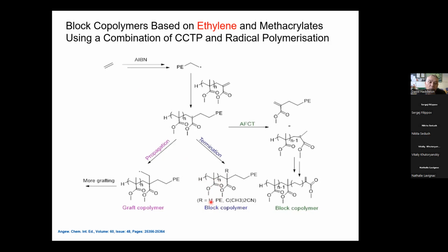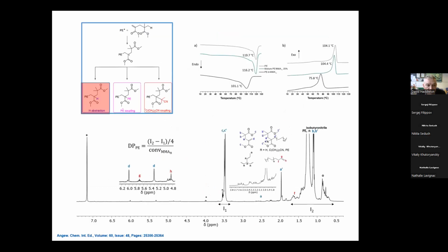And we also decide the composition of the other block, because we can make a butyl methacrylate, or we can do statistical polymerization with methacrylic acid, or we can do the addition fragmentation method, which is what happens with methacrylates. Turns out we get the abstraction, and I'll go through how we distinguish between these three in a moment. So the polyethylene adds there, that radical then abstracts a hydrogen atom from somewhere, and we end up with an AB block copolymer. One of my favorite bits of evidence is the DSC.